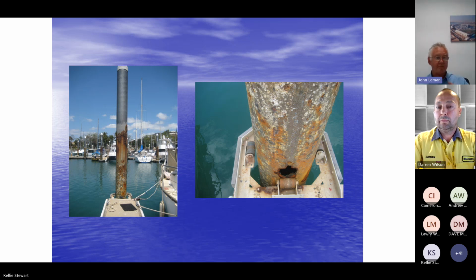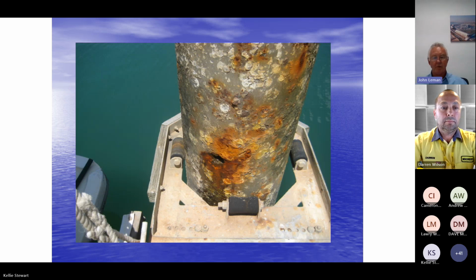Here are some examples. This marina is over 30 years old, and the high build epoxy coating has degraded over time. The one on the right there shows a bit of microbial action, I suspect as well. It's just a hole right through the pile. And another example where we could say the epoxy coating isn't doing too badly, but it has these localized corrosion areas that, in this case, have gone right through the pile. And then of course you've got corrosion on both surfaces of the pile, inside and outside.